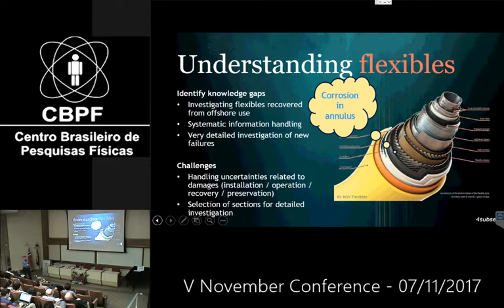This vent gas is one of the things that we use for having control of flexibles, and we do annulus testing to measure the free volume in the annulus. And we can do also vent gas composition, and Laurie showed some examples of that. On the flow lines, then there are only gas relief valves used. That is just popping up, so we don't have the same possibility.